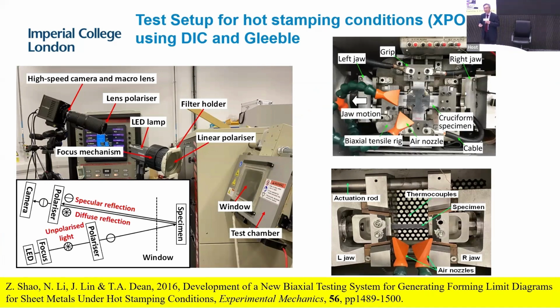And what we do is we use a Gleeble material simulator. Probably people will know this. This is the 3800, and the machine was developed in America by DSI, and we bought this and developed various kinds of techniques based on these facilities. Firstly, we create the specimens. Here is the tensile specimen and the biaxial specimen. And we paint the specimen and use the camera. Probably you have heard about the DIC method, digital image correlation scheme, to collect the data to work out the strain fields.